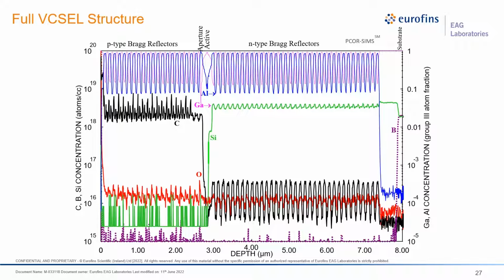If the DBR is to provide good current injection, it must have low electrical resistance. Realizing this in a manner that produces a good device is not trivial. Large energy band offsets between the high and low index semiconductor layers of the DBR can inhibit current flow, particularly for the P-type DBRs. And the obvious solution of increasing the dopant to lower resistance is not an option because this increases optical absorption. A far better approach is to grade the AlGaAs composition at the interfaces while varying the doping profiles at these points. And in due course, we'll show how PCOR-SIMS is uniquely capable of measuring the subtle alloy grading and interface doping profiles.